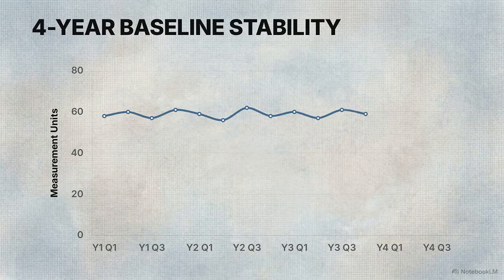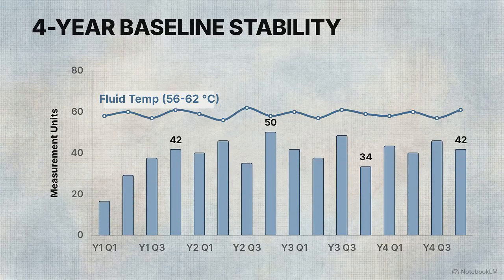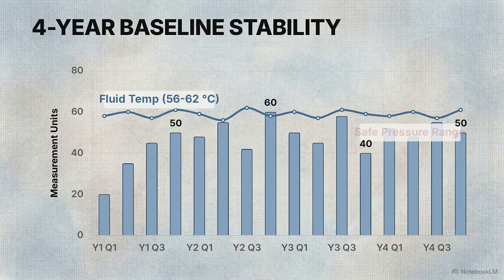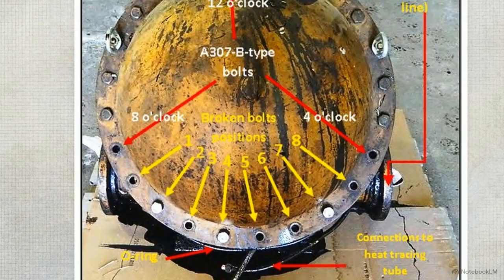Prior to the shutdown, this specific meter had been operating continuously for 4 years. The fluid temperature held steady between 56 and 62 degrees Celsius, with standard low-pressure operating parameters of 40 to 60 psi. This post-shutdown photograph reveals the primary forensic anomaly, an unbroken sequence of 8 heavy-duty bolts fractured along the bottom edge, positions 1 through 8.